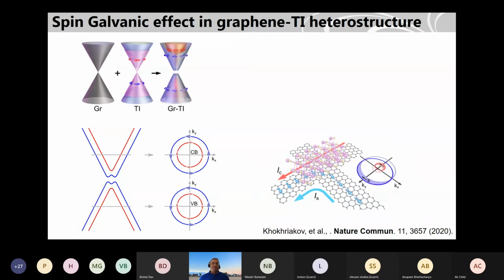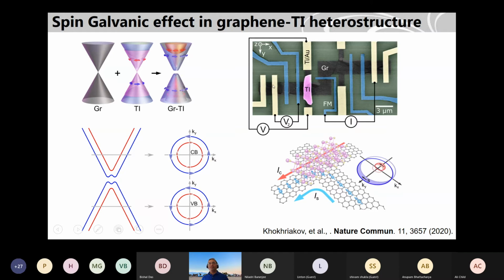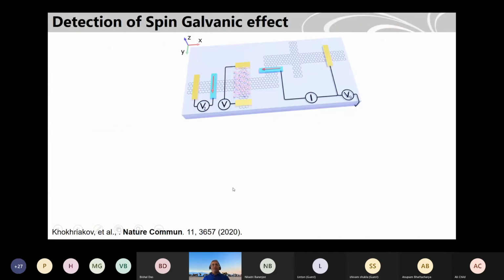Then we thought to make a practical device to use that spin-orbit coupling. What we did here is make a Hall bar type of structure like this. This is our graphene, and this is a topological insulator on top. Then we have different contacts: the blue ones are ferromagnet, and the yellow ones are titanium-gold. What we wanted to see is, let's say we create such a spin splitting in the graphene, we wanted to detect that. So the experiment looks like this.